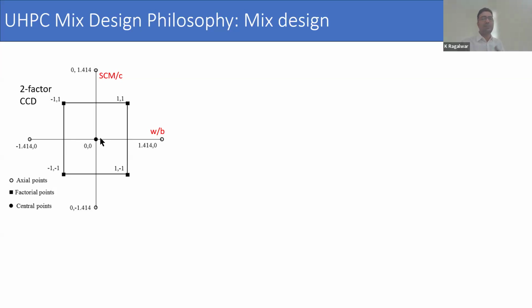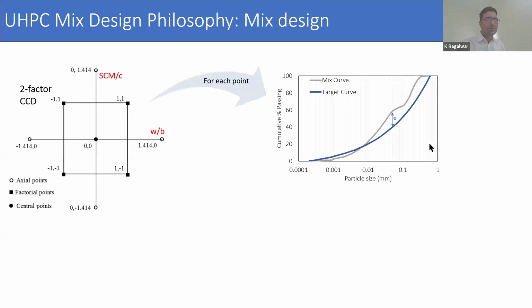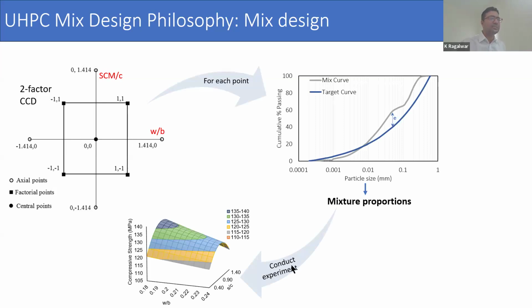This is a philosophy that is commonly used in experimental design whenever our experiments are conducted with 2 factors. And then for each point, we do a mix design, which I talked about in the previous slide. That gives us the mix proportion. And with those mix proportions, we conduct experiments, we measure compressive strength, workability, or any response. That response can be plotted on the Z axis, and the factors that we chose for the experiment can be plotted on the X and Y axes. So it gives you a quadratic equation relating the response, which can be compressive strength or workability or any other parameter, with the factors that we chose.